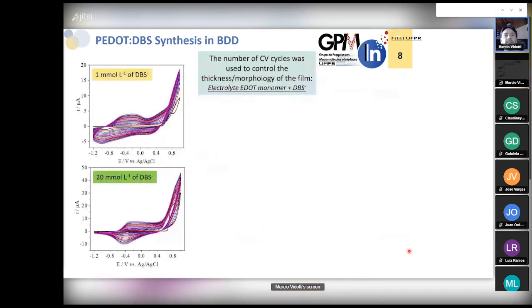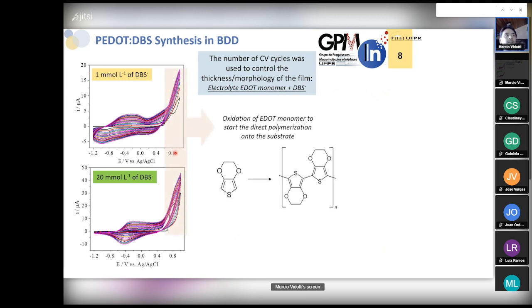And to synthesize this polymer, we have used the electrochemical profile, as you can see over here, and two different regions are very clear to observe. This one at about 0.8 volts is very important for the oxidation of the EDOT monomer to get this polymer. As you can see here and here in these voltammogram profiles, below the CMC and above the CMC.